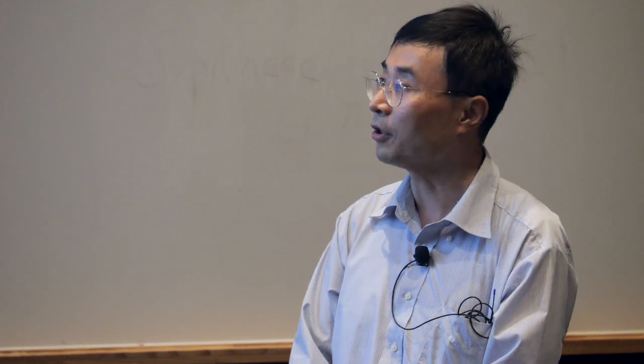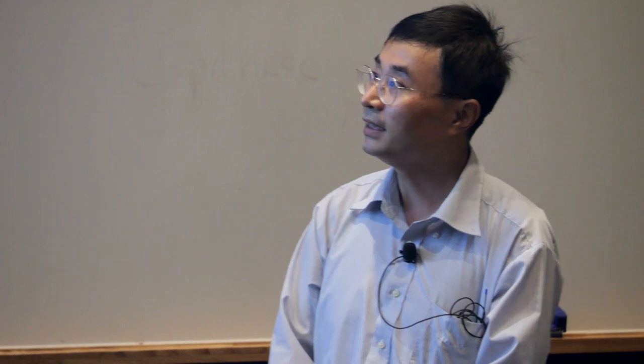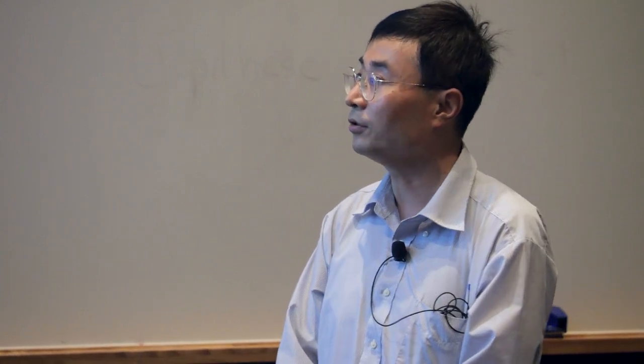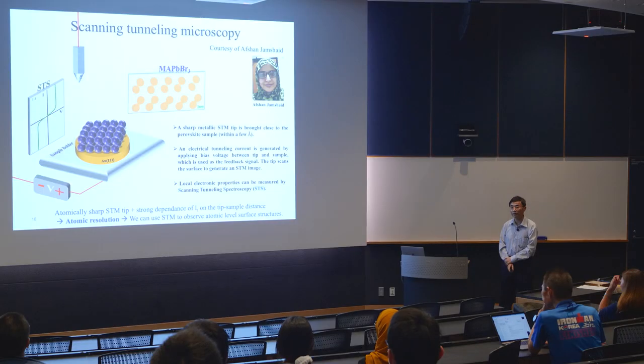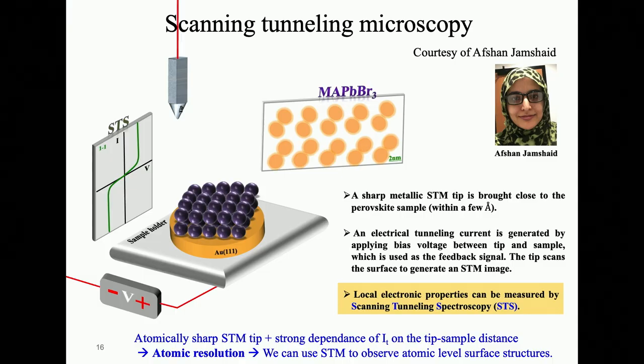Because the STM tip is atomically sharp and the tunneling current has a very strong dependence on the tip sample distance, these STM images usually show atomic resolution. That's why we can use STM to observe atomic scale material properties. Also, we can use a related technique, so-called scanning tunneling spectroscopy, to get more details about the local electron properties of the sample surface.